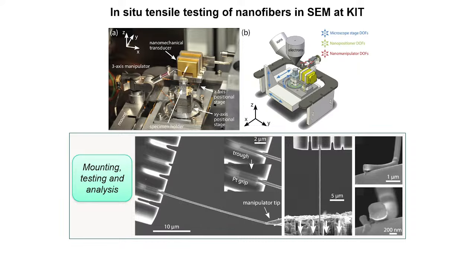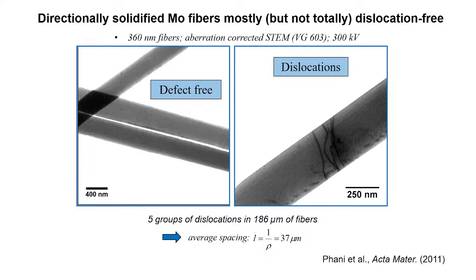And that's in fact what Sudarshan Pani and his colleague showed. So if you look at lots and lots of fibers, you do TEM on them, and what you find is that in many areas they're completely defect-free, but every once in a while you'll come up with little bundles of dislocations that show up, right? So when you grow this as a single crystal, it's not a perfect single crystal. So every once in a while there'll be defects in there, and Phani was able to very painfully measure the average spacing between this group and another group over here, and the average spacing was about 37 micron, which will be roughly 1 over the square root of the dislocation density.